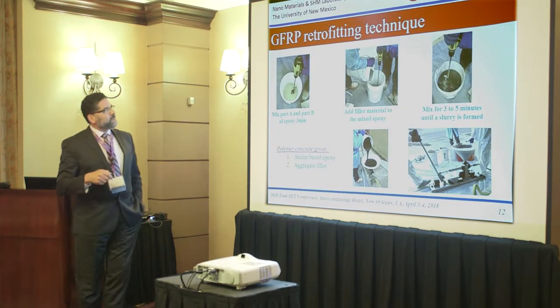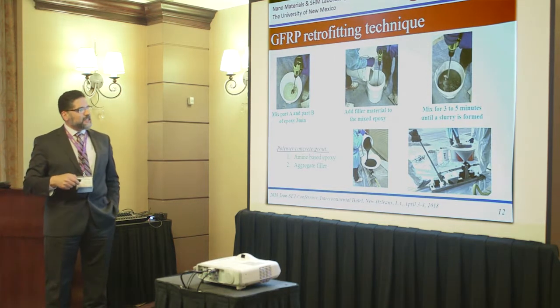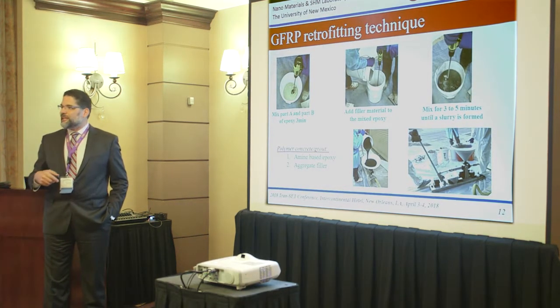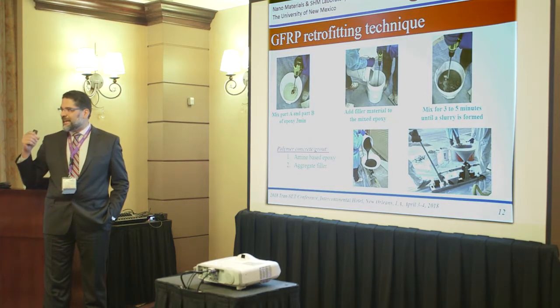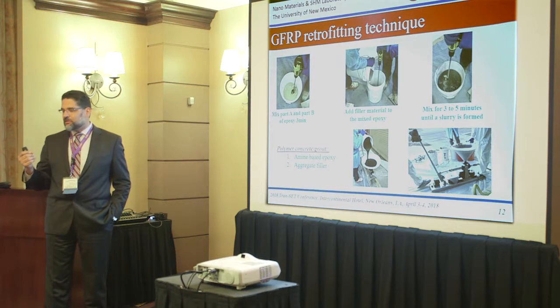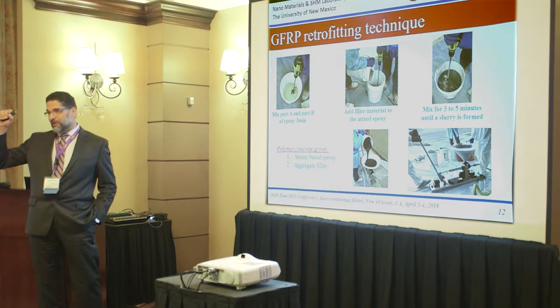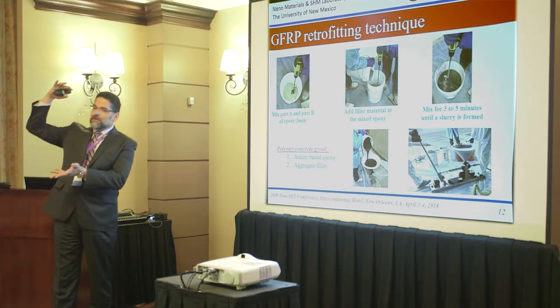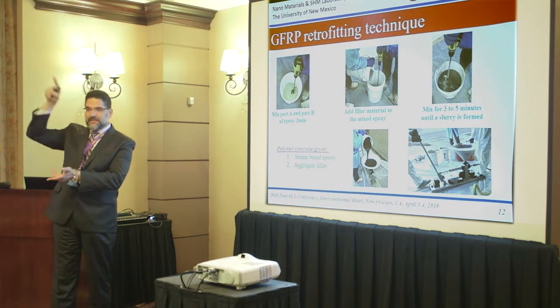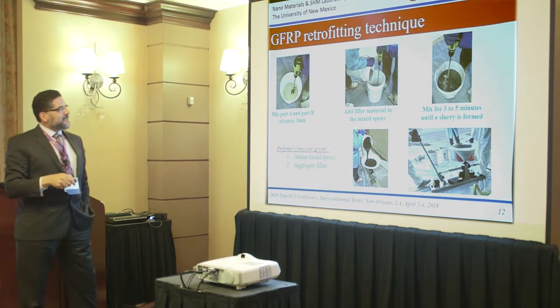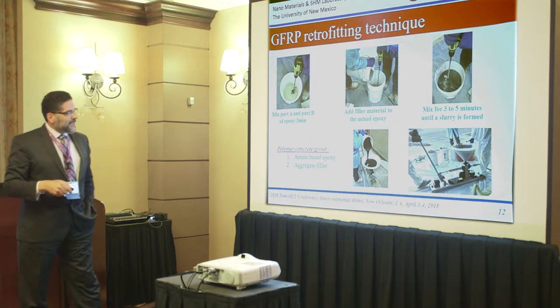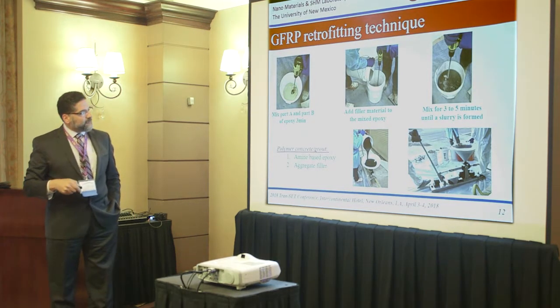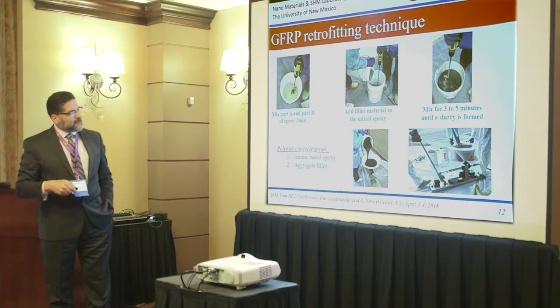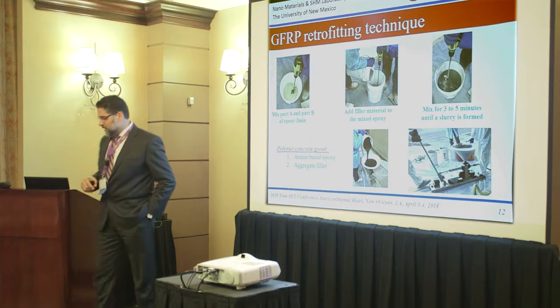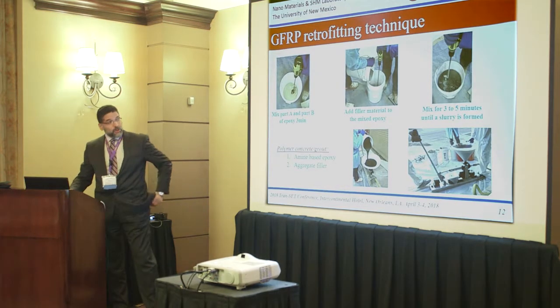So this is producing the polymer concrete. We have an epoxy resin. We've done about 10 trial mixtures until we reached the trial mixture with the polymer concrete that has the required shear strength, the good bond with the GFRP, and also good flowability to allow it to flow in the gap, because we have a very thin gap. We have less than 1 inch, because this is talking about inner diameters, but we have corrugations in the steel pipe. So we mix the materials, add filler, 3-5 minute mixing, and basically it's an amine-based epoxy similar to the GFRP, and then we have this hand pump which can be easily used to pump the material. And again, trial mixes were required to make sure that will work.